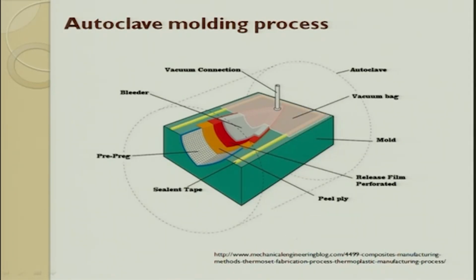So whatever we studied in vacuum, you have put a bleeder, you have put a releasing film, you have put a peel ply, then you have put a prepreg. This is a bottom die. So on the bottom die, you put everything as though you are making a normal composite: a releasing agent, then a bleeding agent, then a bag, everything. Then the entire composite on top of this bleeder bag is covered with a vacuum bag. This vacuum bag is sealed by a double sealant, so that you make sure there is no leak of air, and then you make a vacuum connection.